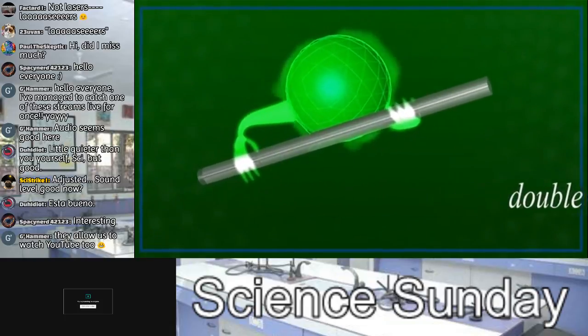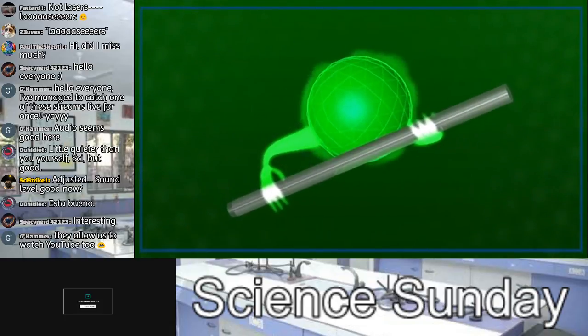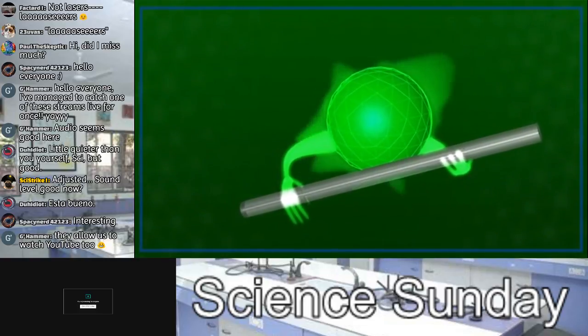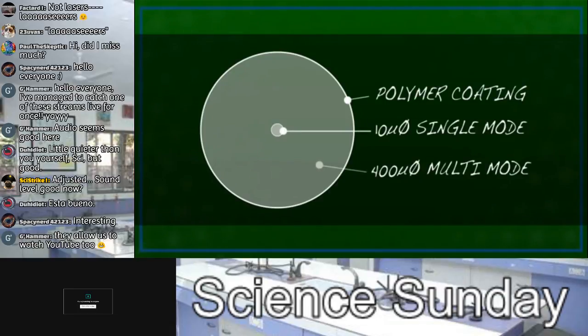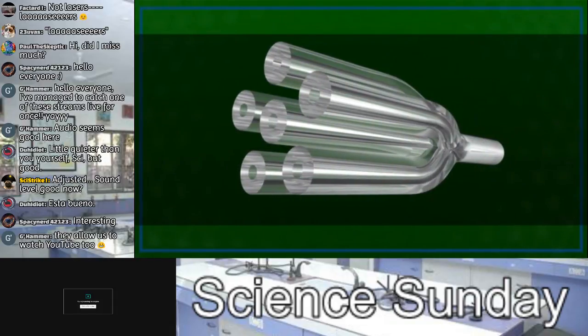Using these economical pumps requires the use of double-clad fibers. The invention of double-clad fibers enabled very high-power fiber lasers with good manufacturing economy, great electrical efficiency, and astoundingly high brightness. In principle, a double-clad laser fiber works the same way as the conventional fiber we just described. However, the double-clad fiber is larger in diameter and has a second pump cladding with a very high numerical aperture. Now, even conserving brightness, this will allow a coupler with six legs at 0.22 numerical aperture each. Pumps of up to 600 watts per leg are commercially and competitively available for this coupler.